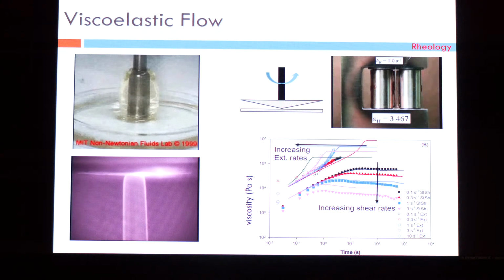So when you do these measurements, you can get one of these various graphs that I have shown on the bottom, let's say something like a viscosity versus time. So imagine an experiment where I have taken this polymer liquid between these two plates, the cone and the plate, and I started rotating one of the plates, and I'm measuring as a function of time what happens to the viscosity.